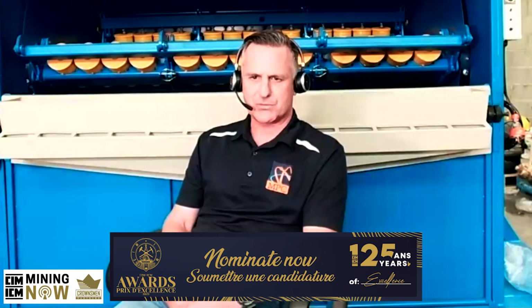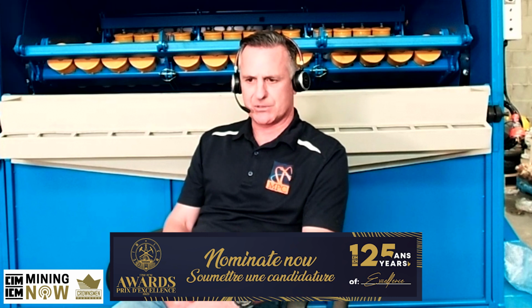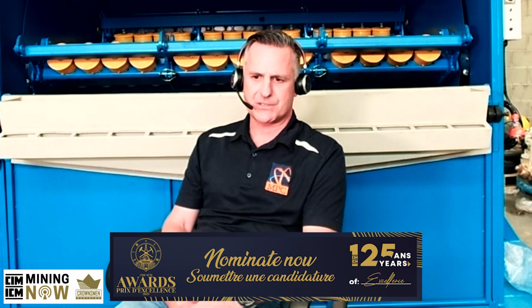So the fallback of the bottle roll test is, like I said, it takes 24 hours, 48 hours, upwards to 96 hours sometimes. This is where Leachwell came into it, and originally what we were doing was pushing the Leachwell 60X to the market, where you add a quantum of that material into the bottle roll and it accelerates the cyanidation process. So rather than taking, say, a minimum of 24 hours, it'll take 1 hour. So your bottle roll result is available within that 1 hour.